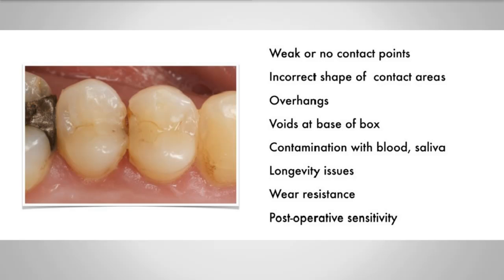Even if there is a contact point, so we put floss in between and it snaps through, the contact area can be the incorrect shape. So you can still get food packing and still get periodontal problems. We see overhangs, we see voids at the base of the box. And then with these composites breaking down over a period of only a few years in this case, it's often because of contamination with blood or with saliva. This obviously leads us to longevity issues.